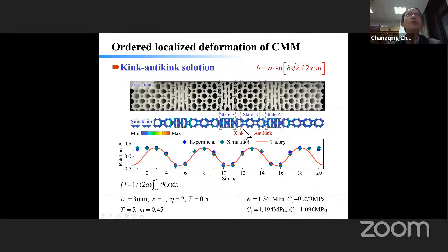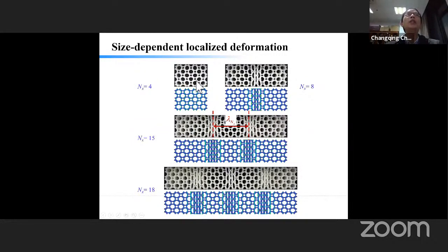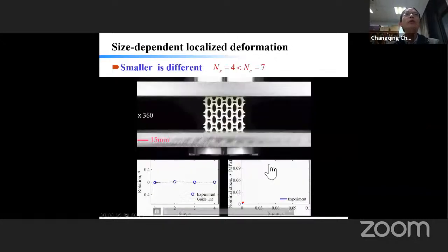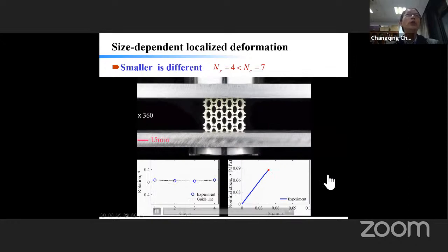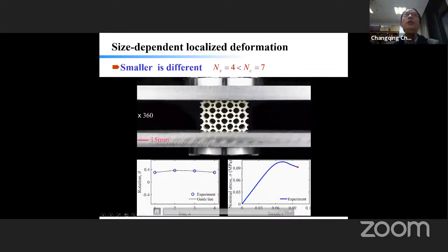Okay, so the question is why people haven't observed such unusual behavior before. I think the main reason is the specimen size is not big enough. If in the transverse, horizontal direction we have four unit cells, you actually cannot observe localized deformation. When the size increases from 4 to 8, you are able to observe one localized deformation zone. If you increase the size further and further, you are able to observe highly localized deformation zones that are regularly distributed. Here is an example for a small size: you only observe uniform deformation, which agrees with our simulation.